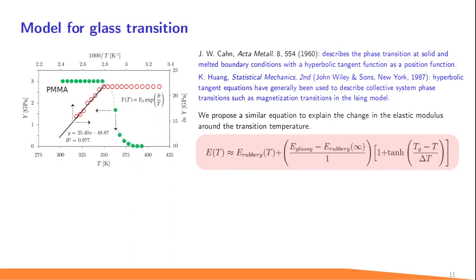Since we have considered the change of elastic modulus on temperature as a phase transition at the boundary in the temperature coordinate, we propose a similar equation, tangent hyperbolicus, for describing the variation of elastic modulus around the transition temperature.